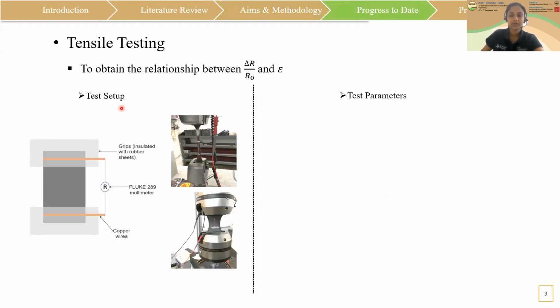So moving on to the research carried out to this date, to characterize the material, tensile tests were conducted to obtain the relationship between the relative resistance change and strain. The resistance of the material was measured while the sample was being extended.